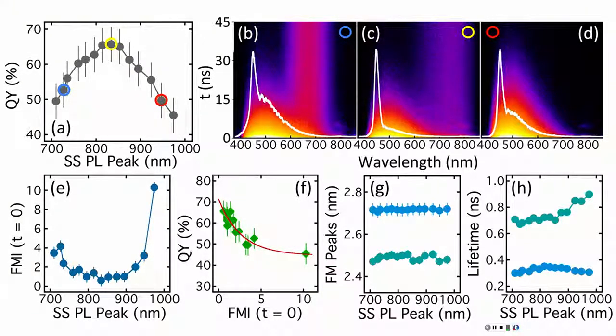So they're actually really big, but the core is really small. So when they go to do the gap versus size, they use the big size, right? And the big gap, and it skews the whole curve off. That's the first thing we noticed was, God, these dots are small for red emitters. That's because they've never seen oxygen, right? Anyway, let me know if you have any insight, okay?